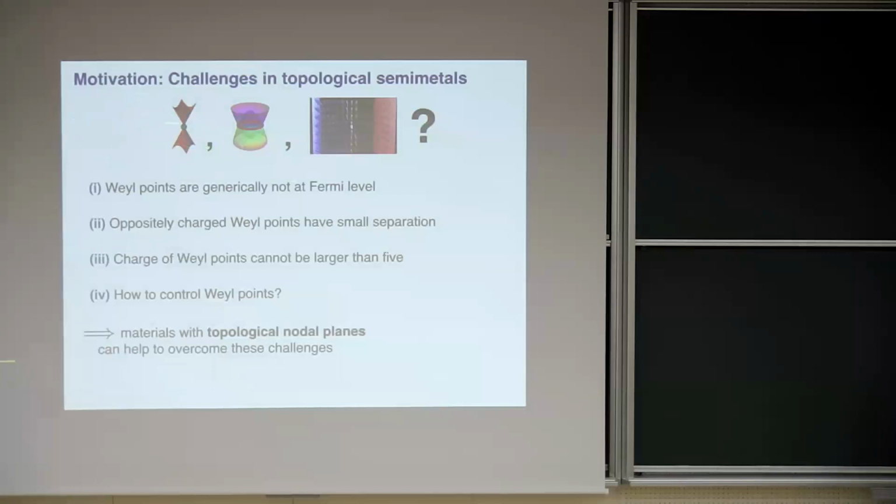This is an example of a topological semimetal, but this special crossing protected by topology can also have higher dimensions, so it can also be one-dimensional. In so-called nodal line semimetals, one has two parabolic bands which overlap with each other, forming a ring where you have a twofold degeneracy. These types of semimetals have been studied a lot.